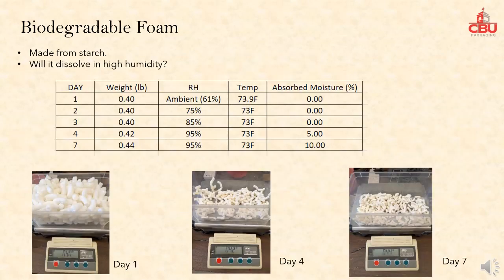Since biodegradable foam is made from starch and starch dissolves in water, a study was performed to see if biodegradable foam would dissolve under high humidity. In this case, 95% relative humidity was used, since it is the maximum the environmental chamber can produce.